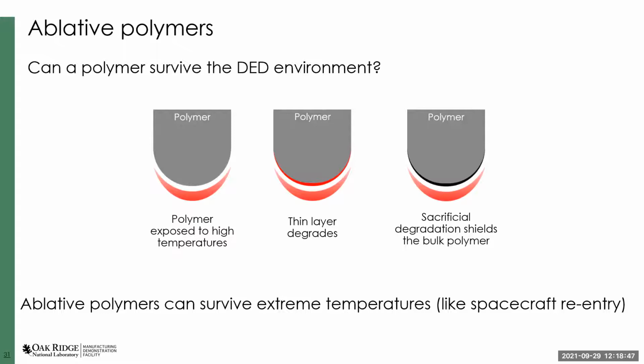It's unreasonable to expect any polymer exposed to very high temperatures, things like being blasted with a laser or getting molten metal dumped on them, without some kind of degradation. But the goal with ablative polymers, and what has been achieved by some of these polymers, is that you have a thin layer of the polymer that degrades, and the degradation of that layer results in some kind of shield that protects the bulk of the polymer from further degradation. Basically you have a char, usually in traditional ablative polymers made mostly of carbon, which can resist much higher temperatures than the original polymer. And that carbon char will protect the bulk polymer from the rest of the heat.